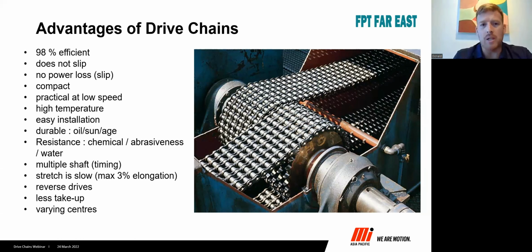It's usually lower speeds. And that's important to notice. The higher speeds, then you face lubrication issues. You face some other centrifugal force challenges. So it's usually lower speeds. They can handle high temperature. You know, it's metal. They can typically go up to above 250 degrees without too much challenge to the material structure. Once you get higher temperatures, important to consult with us because there's usually some sacrifice on the strength of the chain. Okay, pretty durable. You know, they can work outside, wet environments, dusty environments, very durable.